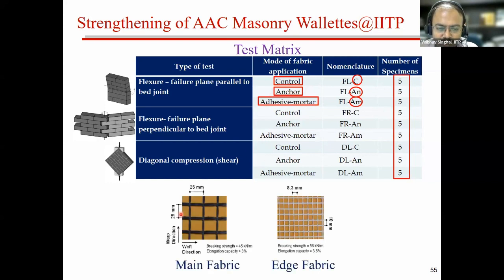So this is the fabric which we have used. This was the main fabric, having a grid spacing of 25. And this fabric we have placed at the edges because we want the anchors to be easily placed. So for easy placing of anchors, we have used this fabric at the edges, which has a small grid spacing of approximately 8 to 10 mm.